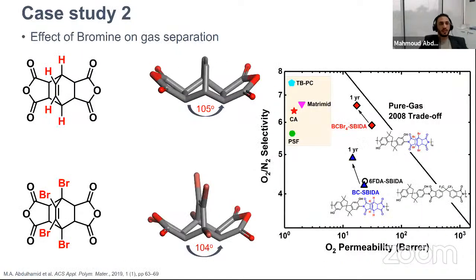Other studies were focusing on evaluating the effect of bromine atoms. For people who know a little bit of chemistry, the bromine atom is a bulky atom. It's a halogen. So we decided to study the effect of introducing different types of halogens. Actually, we tried chlorine and fluorine, and also compared with hydrogen. This material is commercially available. This one is synthesized. Once we prepared this, we ran a simulation to evaluate the angle, and we can see that with and without bromine, we have the same angle, 105, 104. So it's more or less the same. So any effect observed in the final product will result from the presence of bromine.